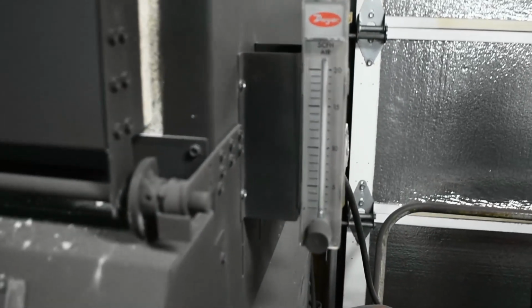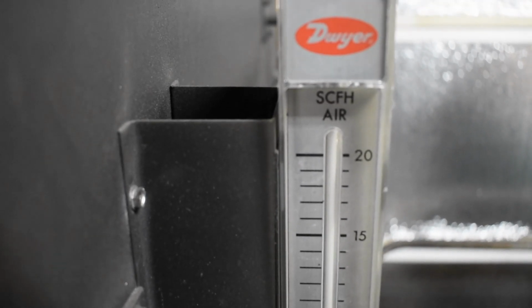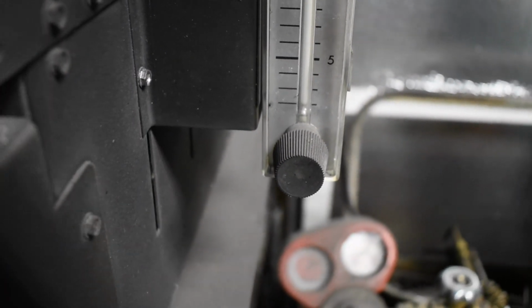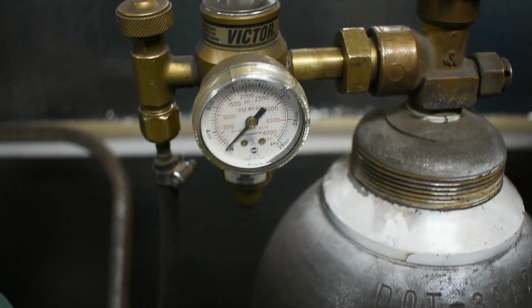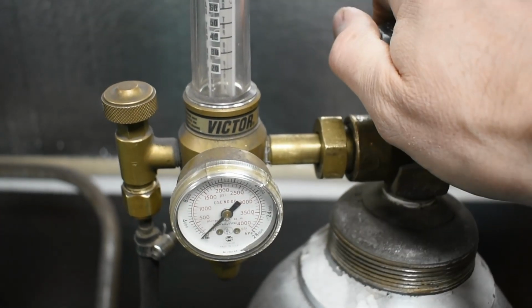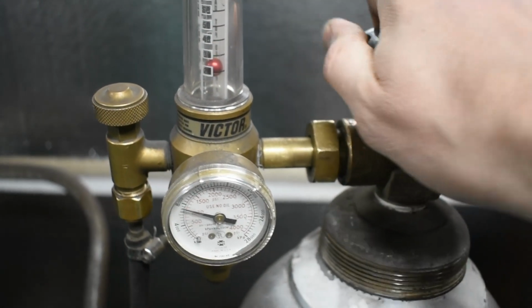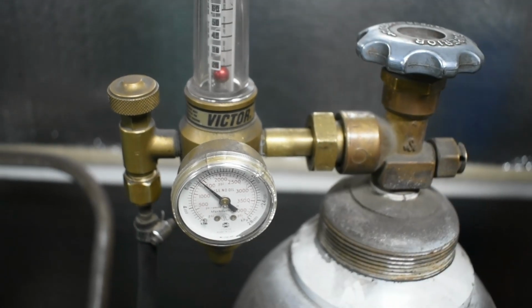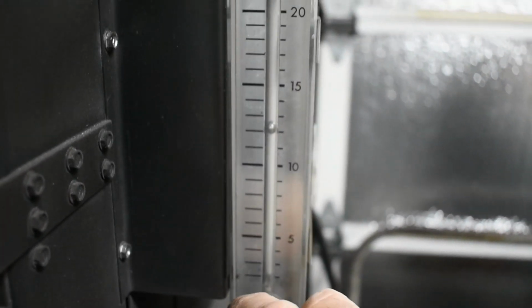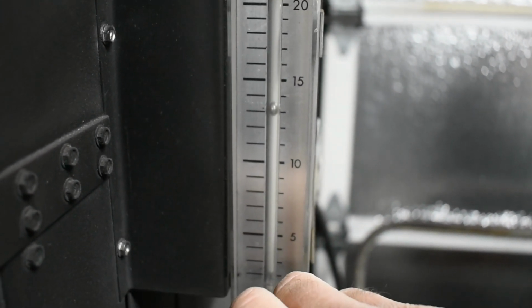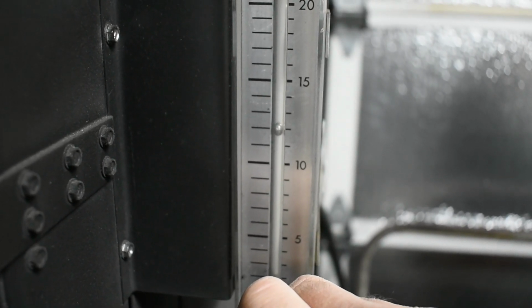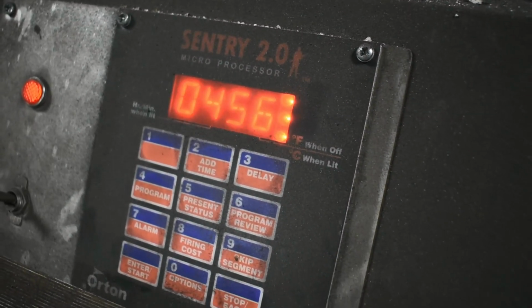This is my Paragon 24-inch double barrel kiln with the argon flood kit, argon purge. There's a flow meter on the side of the oven installed by Paragon. And over here is my Victor TIG flow meter, and this is much the better of the two. It renders the one on the oven pretty much irrelevant, but I still use the oven one to fine-tune a little bit here and there. You can see I'm at 12 cubic feet per hour, which seems to do a pretty good job of getting most of the scale and decarb.